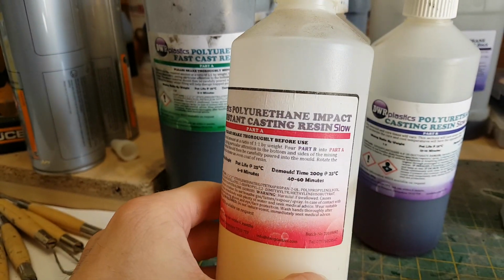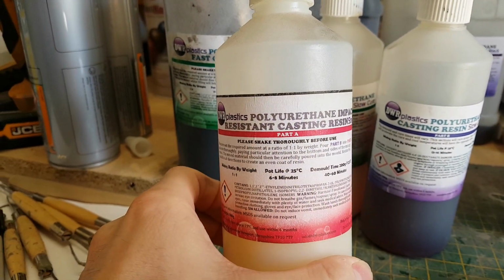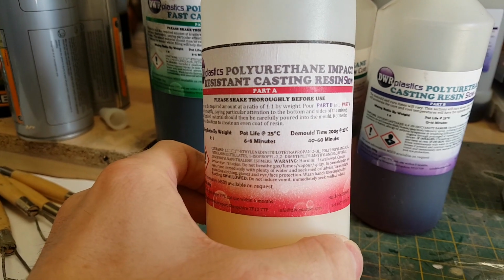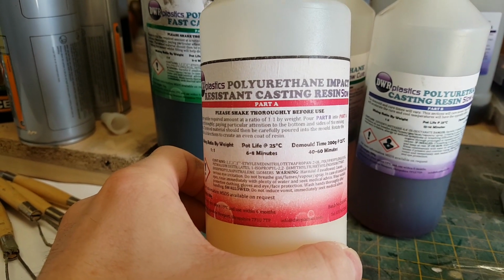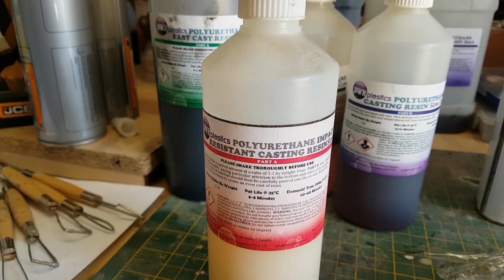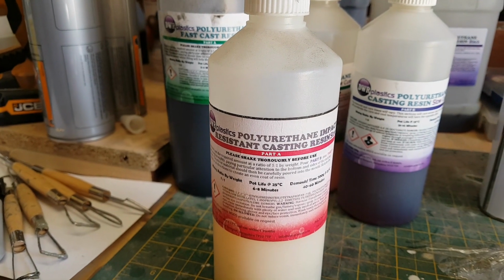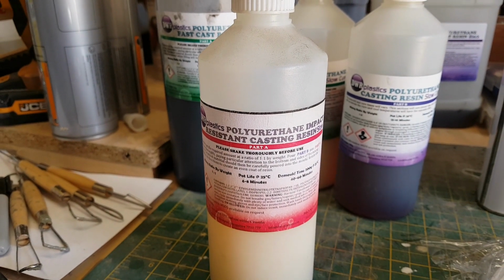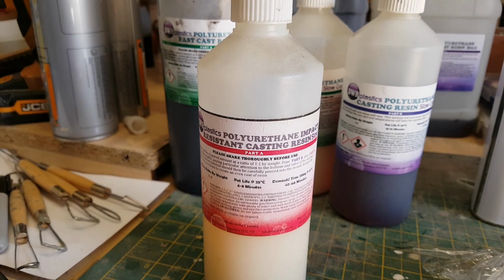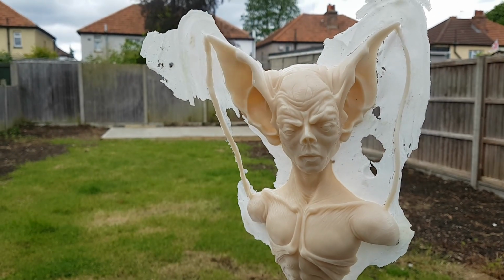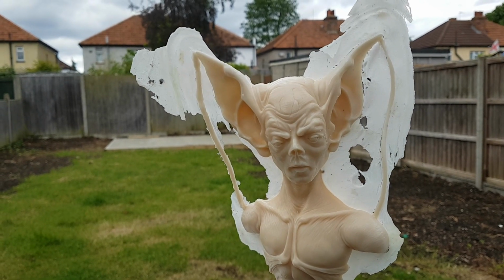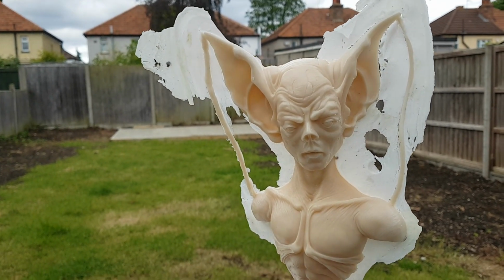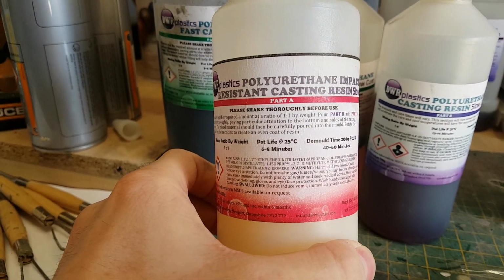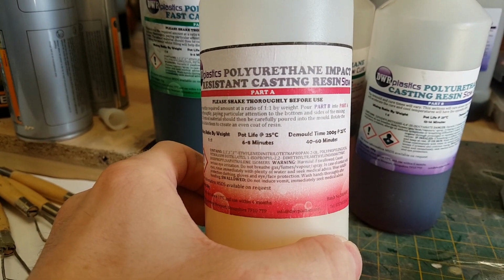There's also this type of resin as well, which is an impact resistant resin. Now, I mentioned that the polyester resin is actually quite brittle, and the advantage of this type of resin is that when it cures, it does cure quite hard, but there's also a degree of give to the material as well. So if you have any thin pieces on your sculpture, for example this sculpture has some very thin ears, instead of them breaking if they knock into anything, they'll actually bend slightly, and that's quite useful if you do have thin pieces like that, or perhaps some delicate casts that you need to do.